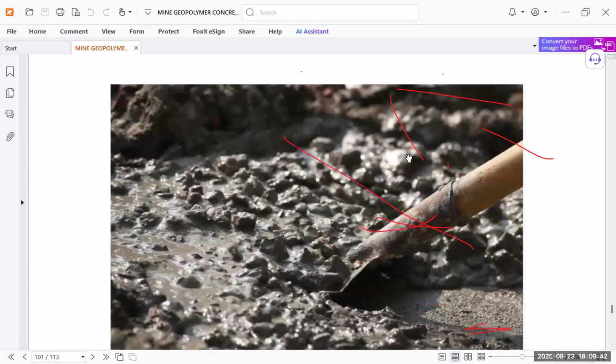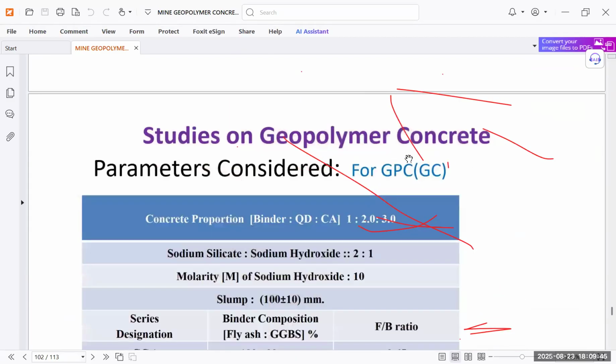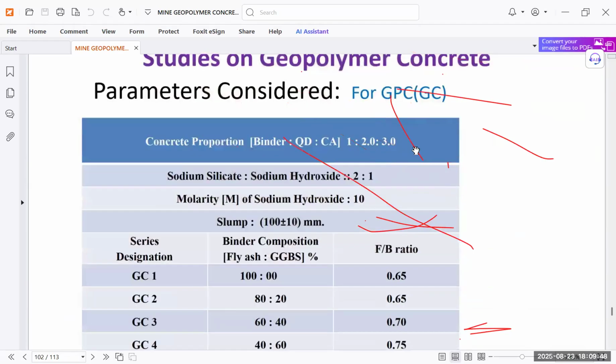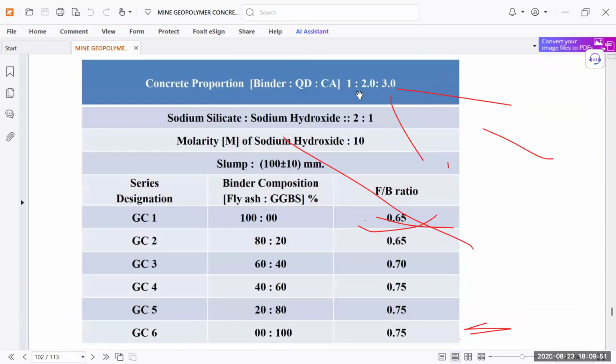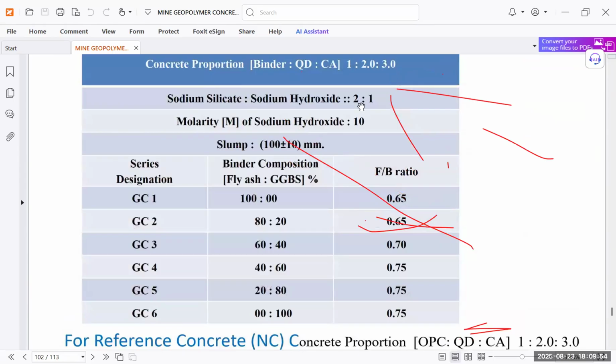So this is the geopolymer concrete which has been made. And these are the studies on the geopolymer concrete. The parameters considered for geopolymer concrete are concrete mix proportion 1:2:3, and sodium silicate to sodium hydroxide ratio is 2:1, molarity is 10. So we have to take care of the sodium hydroxide ratio and the molarity. Then slump is 100 plus or minus 10. And this is the series we have made. Binder composition ratio, fly ash to GGBS, is 100:0, 80:20, and 60:40, so different fly ash to GGBS ratios are there. And fluid to binder ratios are 0.65, 0.7, 0.75. So you can see that different fluid to binder ratios are there.